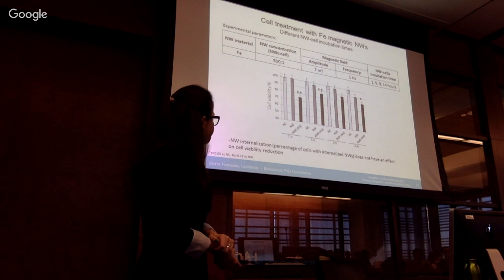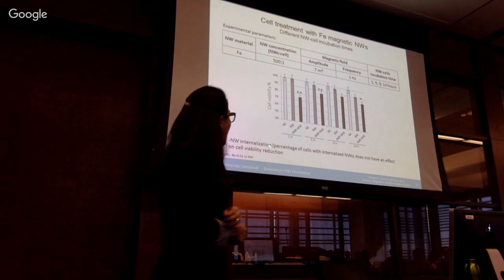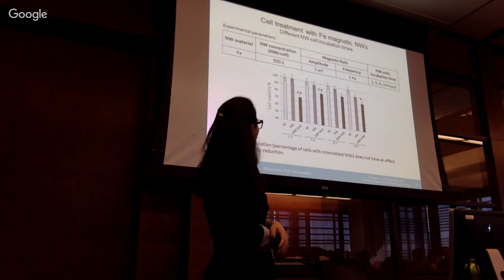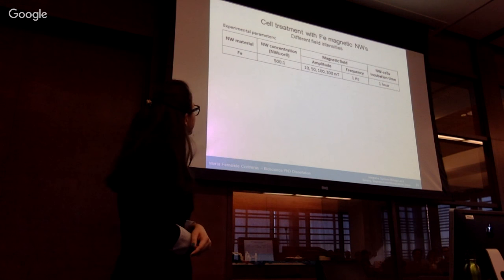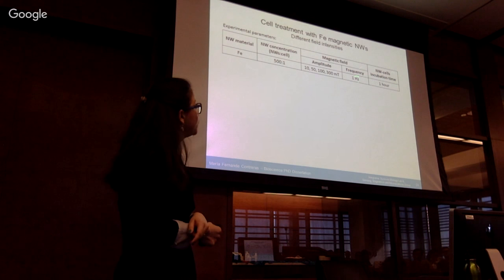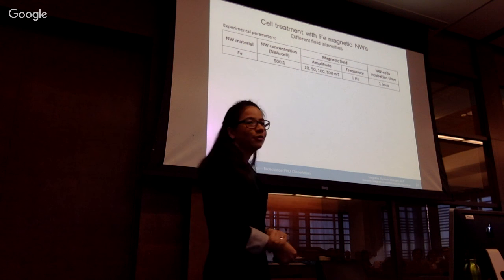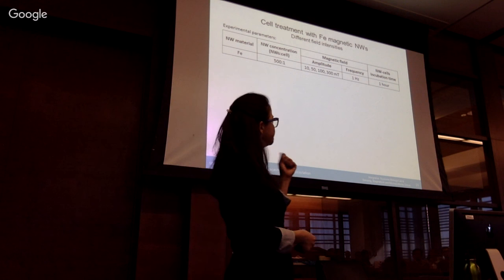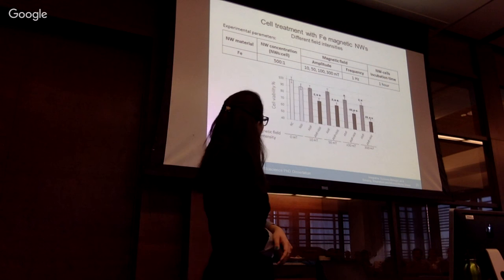So from this experiment, we can conclude that the nanowire internalization, or the percentage of cells with internalized nanowires, didn't correlate with the cell viability reduction. And the final experiment I did was with the same material, concentration, and frequency values. Here I just changed the field amplitude for these four values, 10, 50, 100, and 500 millitesla, and I incubated the cells for 1 hour, as it was the time for which I obtained a higher viability drop. And these are the results.